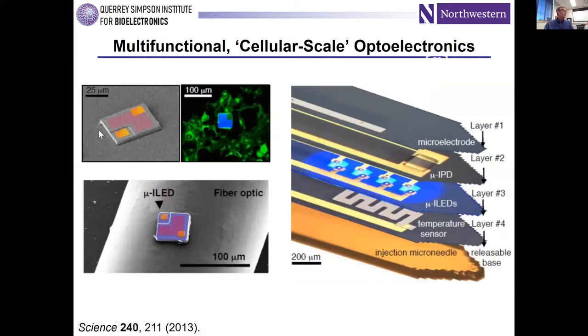And here's an example. Here's a high quality indium gallium nitride blue LED with lateral dimensions comparable to an individual neuron. So it's the size scale of an individual cell, actually much thinner than a cell, maybe a few microns in thickness. And by comparison to the fiber optic cable, this is what it looks like. Here's one of our micro scale LEDs sitting on top of a fiber optic cable of the type that's used in traditional optogenetic studies. So we know how to create these things, same ideas I described in the context of the electronics. We know how to move them around with the stamps, same concepts.